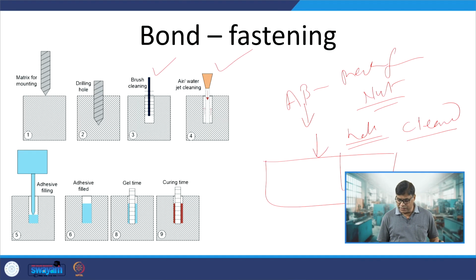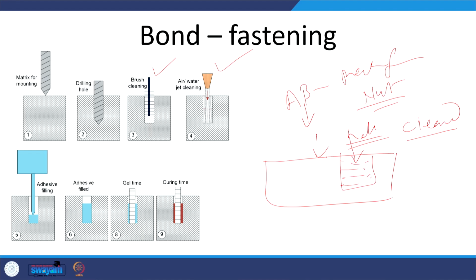Once the hole is created like this, it is filled with the adhesive up to a certain distance. Once the hole is filled with the adhesive up to an identified value, we put the mechanical fastener, that is this. So, adhesive is being filled up to the desired height, then we place the mechanical fasteners like this and allow it to set for some time, that is the gel time, so that the position of the mechanical fastener is not disturbed, and then it is allowed to cure.